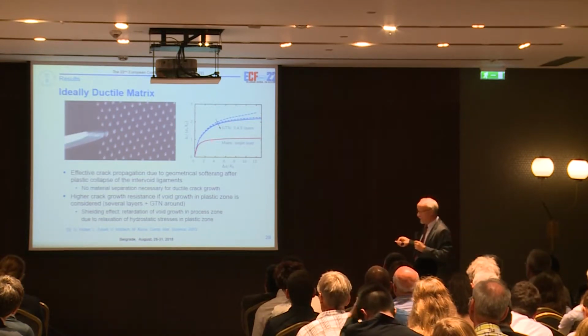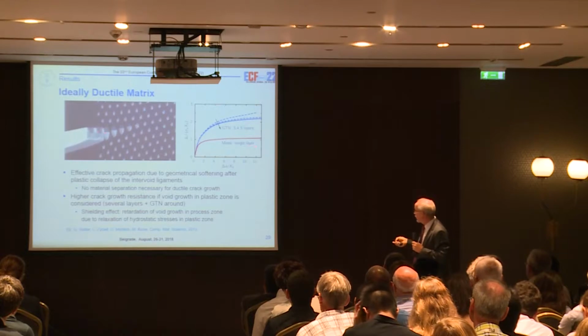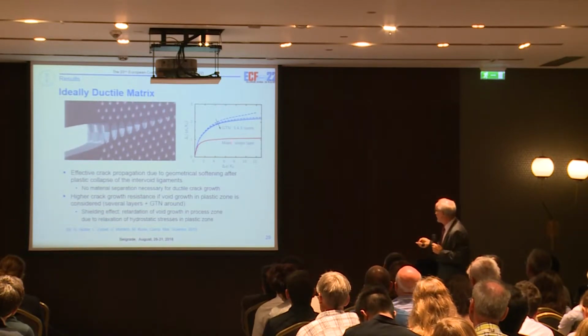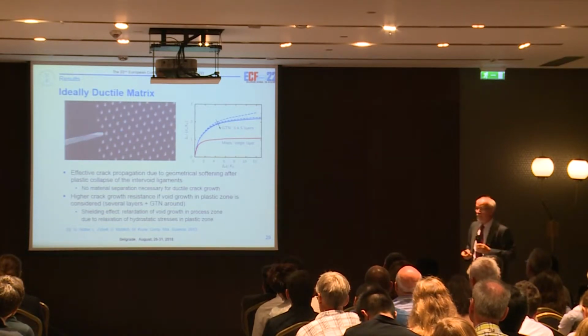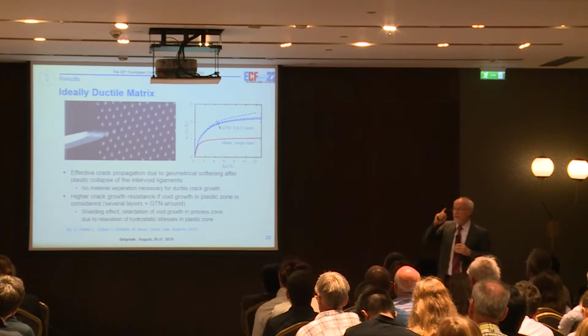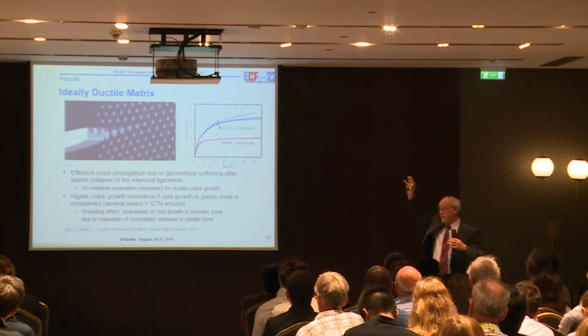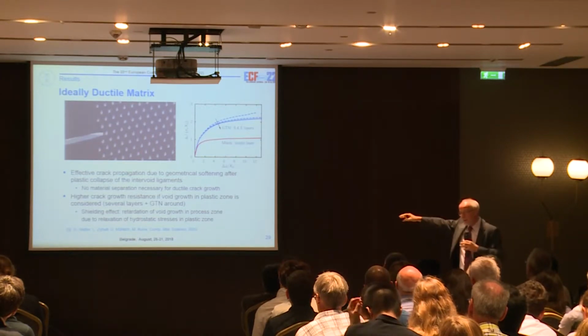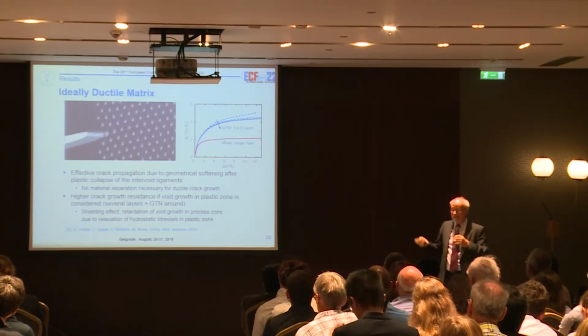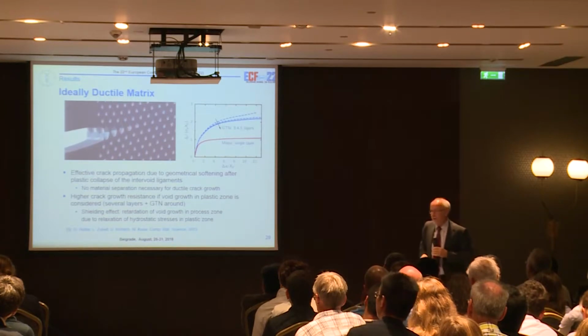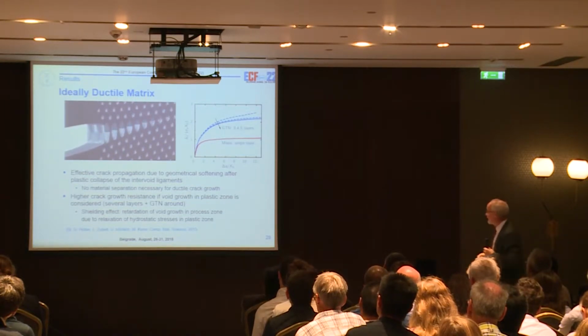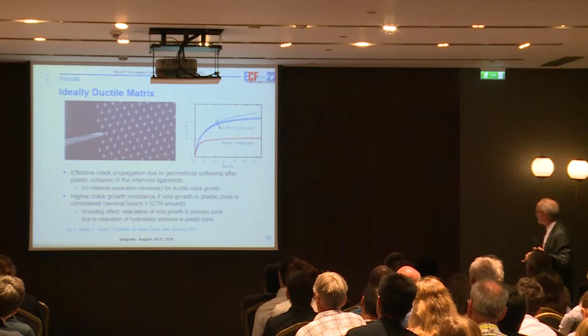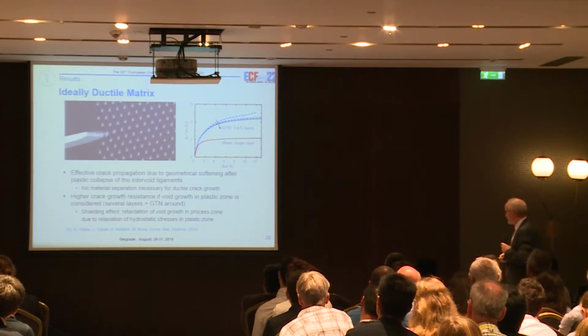Compared to a simple material with only one layer of voids, this gives a toughness increase of a factor of 2. The outer voids reduce the hydrostatic stress state at the crack tip and so increase the toughness, a shielding effect. This has not been considered in previous investigations.